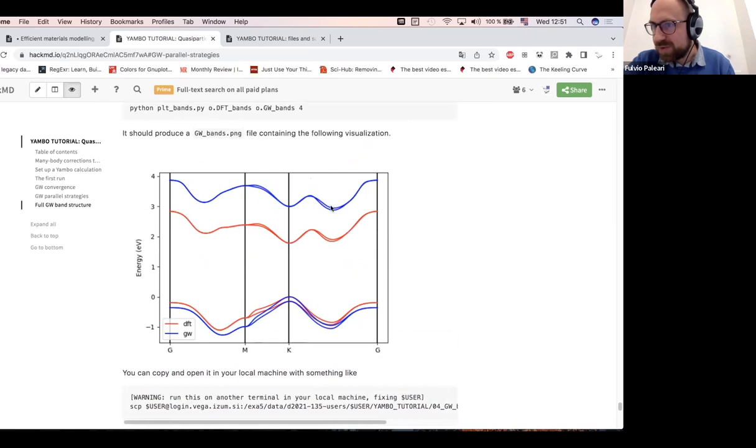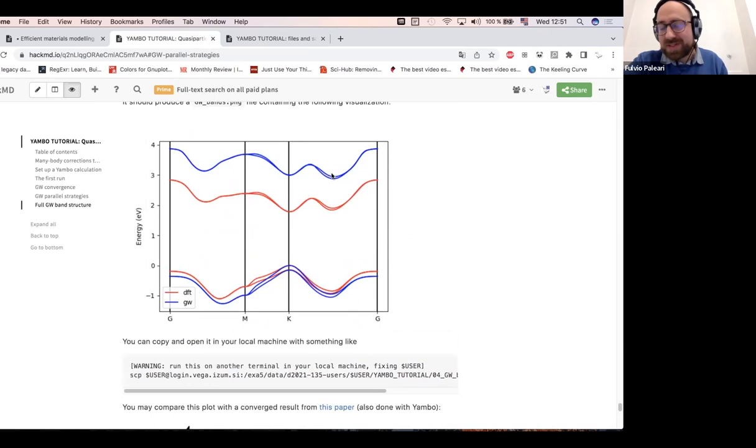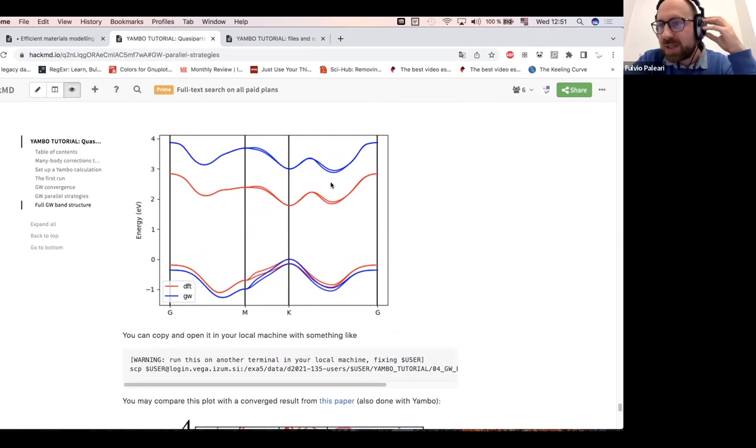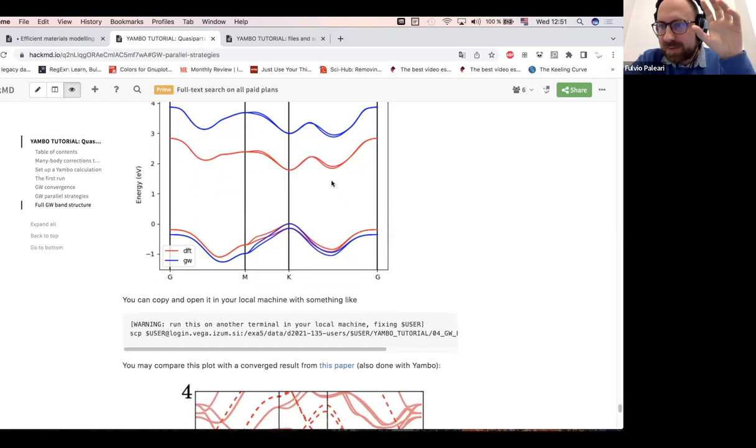And we even used a larger system than in regular tutorials, because we had a lot of computational space. So, just a warning again: be very careful, especially in these systems, transition metal dichalcogenides. It's not just numerical convergence; they are also very sensitive to things like the lattice parameter. If you set the lattice parameter to the experimental value, or optimize it with Quantum ESPRESSO, you may get different relative energies between these two competing minima. It can also change a little with the pseudopotential. This is typical of these TMDs: they are highly studied, but not so easy to study.